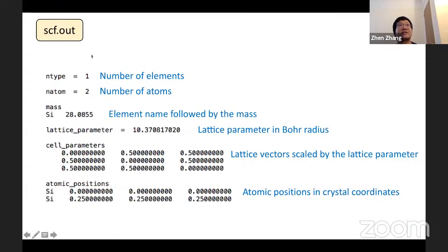So first, let's look at scf.out. ntype is the number of elements, and N-atom is the number of atoms in the primitive cell. For silicon, we have only 1 element and 2 atoms per primitive cell. For the mass tag, for each element, we write down the element name followed by its atomic mass. So lattice parameter is a constant in unit of Bohr radius. For the cell parameters, it provides the 3 lattice vectors scaled by the lattice parameter. And finally, for atomic positions, we write down the atomic positions for each atom in crystal coordinates, following the element's name.